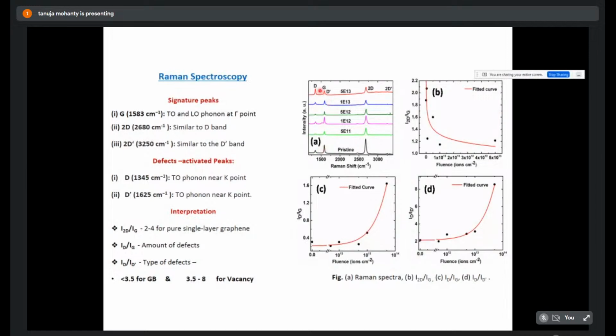So normally Raman spectroscopy, why it is given that this is the spectrum that gives about the signature of the peaks here. Then the defects are there or not, that is the defect activated peaks. One is the D, which is 1345 centimeter inverse, which is seen here. And another is the D dash peak, which is occurring at 1625. So that gives you D dash peak. And then G peak is that, and I2D by IG is 2 to 4 for single layer graphene.